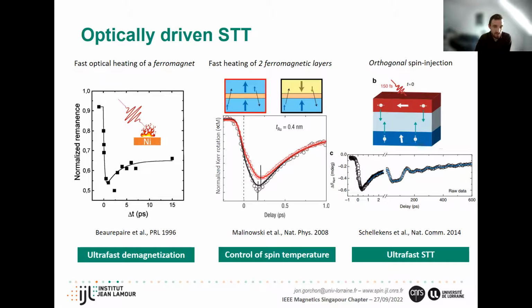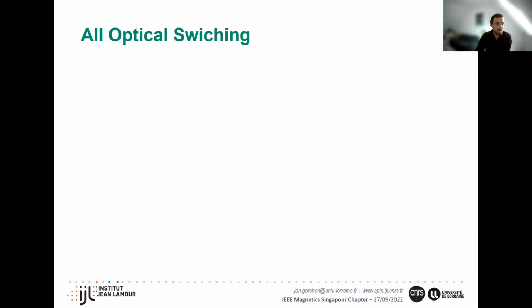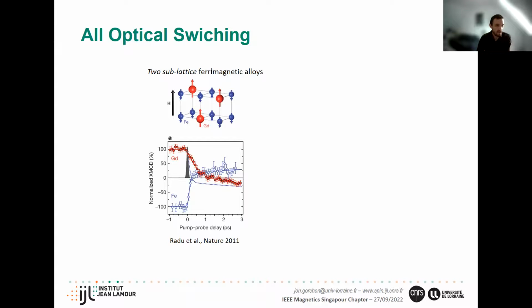So can we use this to actually switch a layer? And so this brings me to what's pretty famously known as all-optical switching, or all-optical magnetization switching. This was discovered in 2011 by a group in Nijmegen. So they discovered that in this ferrimagnet, gadolinium iron cobalt, where you have the gadolinium and the iron cobalt sublattices antiferromagnetically coupled, when you pump this with the femtosecond laser, whether it's linear polarization or circularly polarized light, you get an immediate switching of the magnetization just due to the heating of the lattice, heating of the electrons. And the way we understand this now is that you have an exchange of angular momentum between the 2 sublattices.